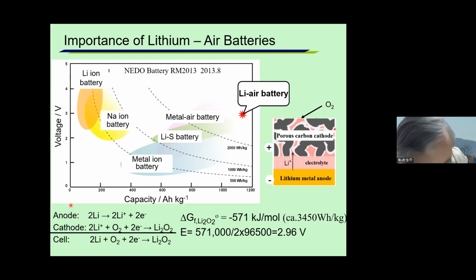So in our group, we are working on lithium-air batteries. This is the capacity and voltage plot, and the lithium-air batteries, as I mentioned before, have theoretically very high energy density because they use only oxygen as active material, and also a lithium metal anode. So by the reaction, lithium becomes lithium plus, and the lithium plus reacts with oxygen, and reduction becomes Li2O2, which is kept in this porous carbon electrode.